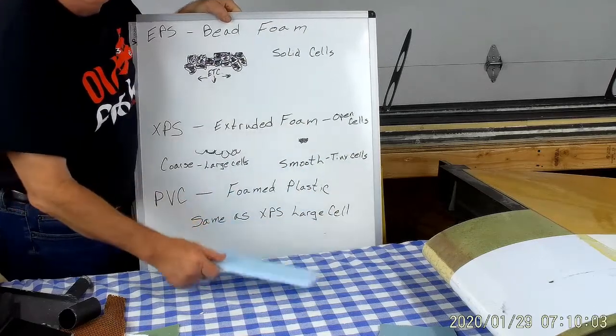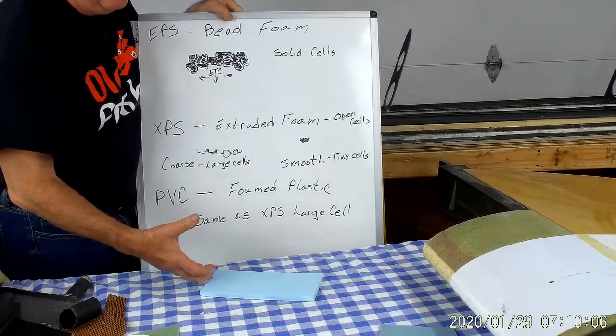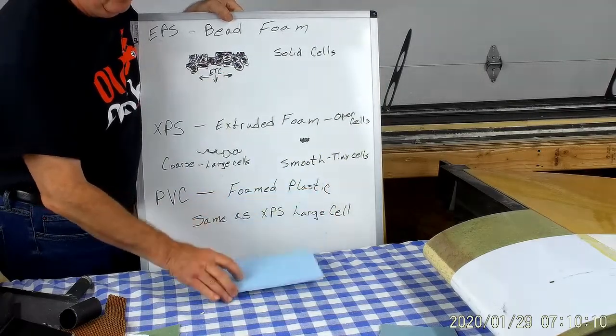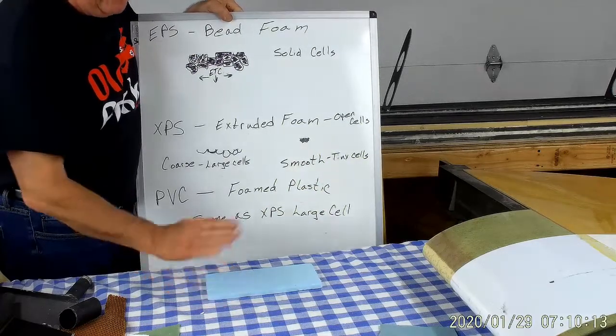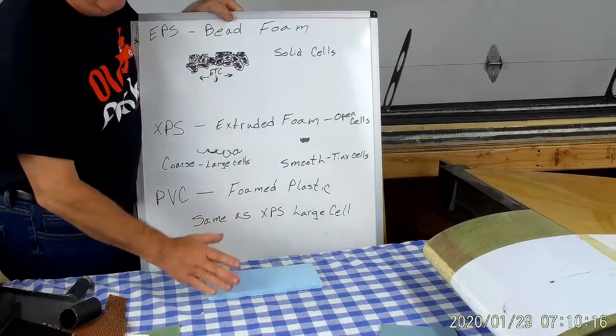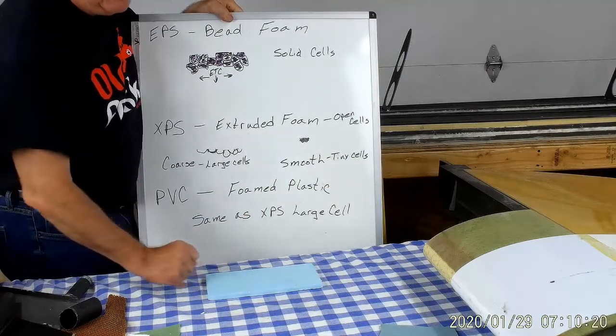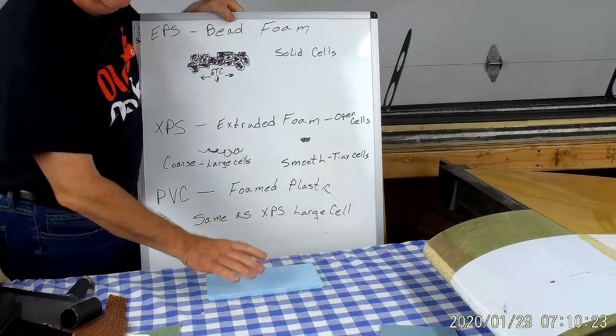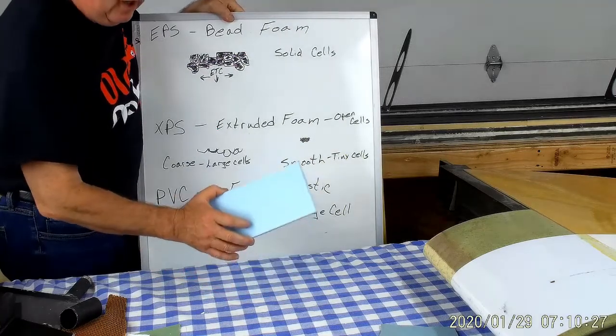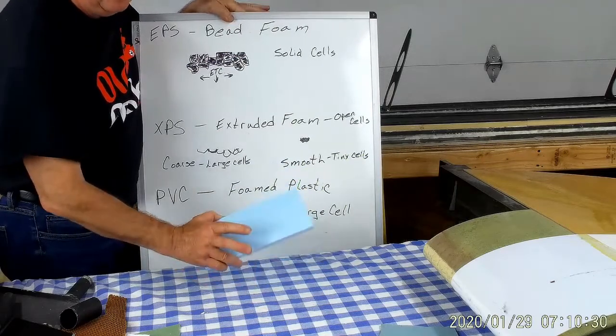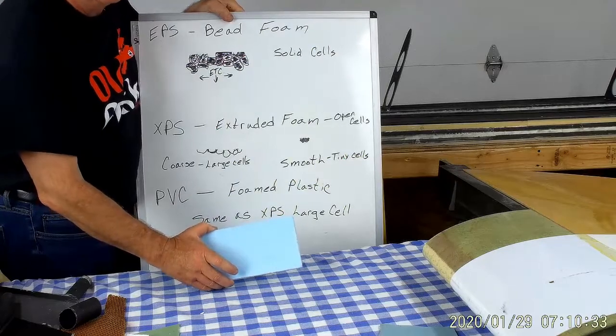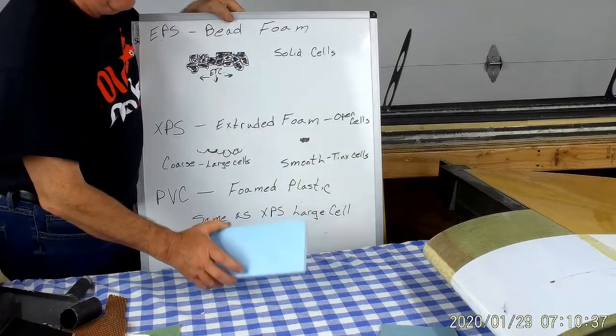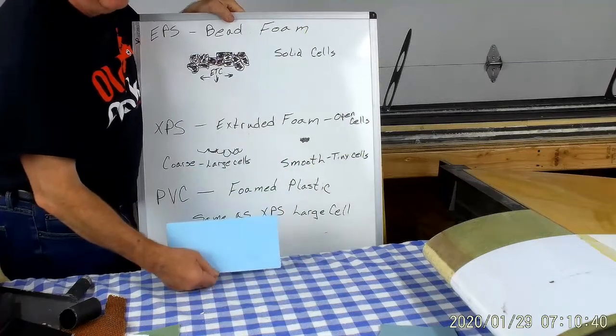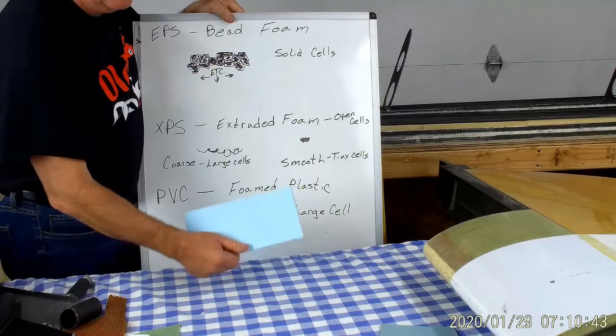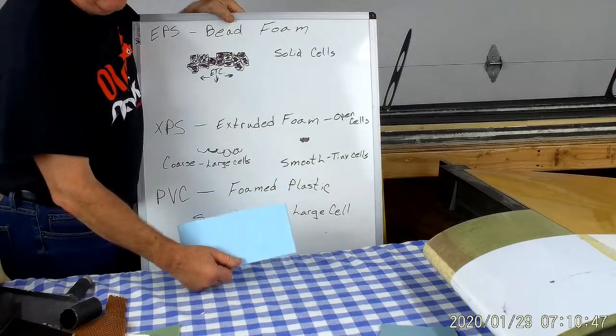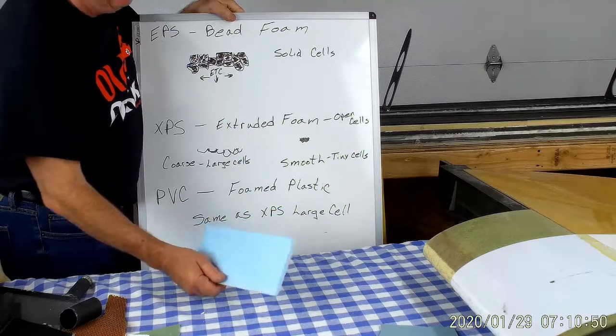So if you go look, I've provided a link to how I built the spars for my current wing, and the spars use this foam as the core, and you'll see that it's done as a wet layup, not a transfer, but a wet layup, and it's not vacuum bagged, and that's why. But I'm able to squeegee off all the excess resin, there's not a lot in the foam, and you really get a good high strength to weight ratio result. So there are purposes and uses for this foam as a quote-unquote structural foam, and it actually has advantages over the other foams that are normally picked for structural components. You just have to make sure that you design it such that there aren't loads imparted to the foam that it cannot handle. And in most cases, it's fine.